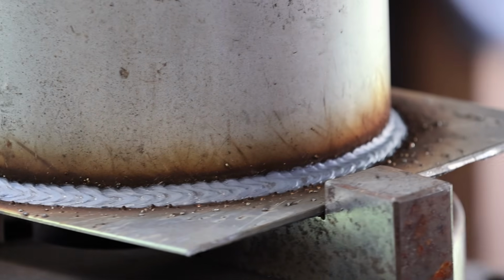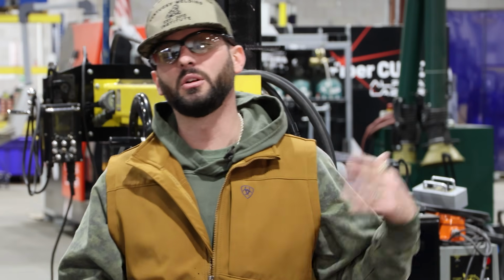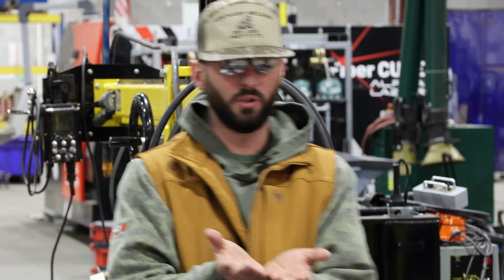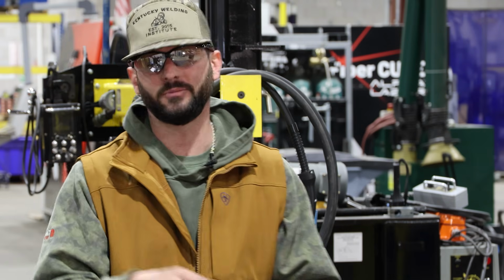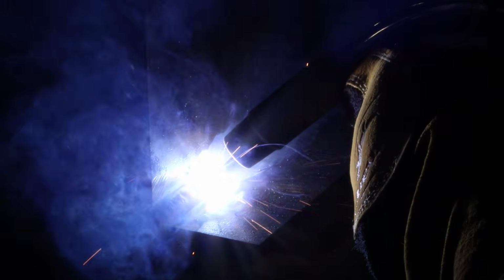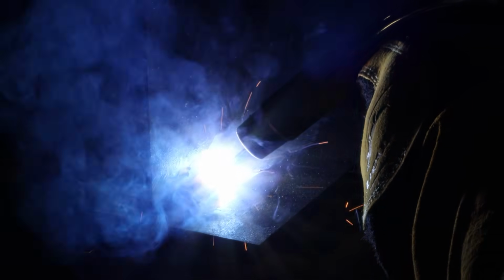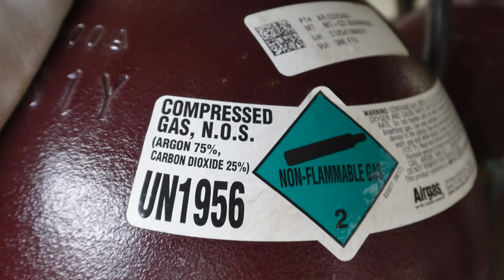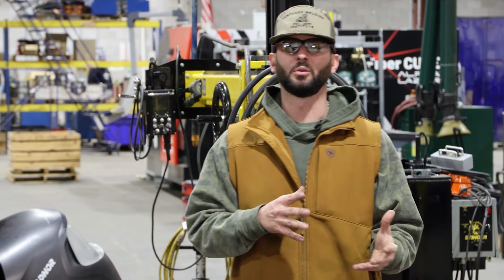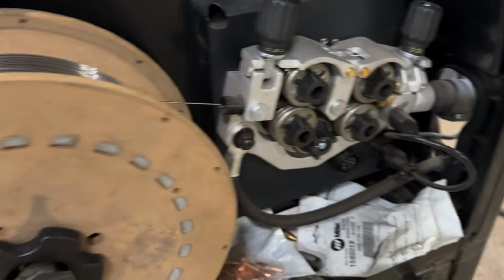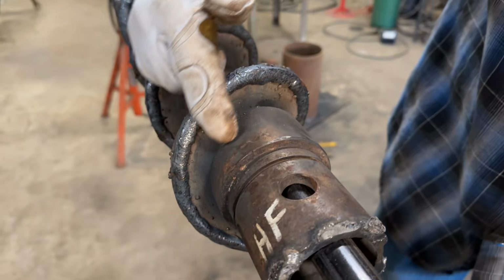Now, when it comes to flux core arc welding, especially dual shield, which requires an external shielding gas along with the flux on the inside of the wire, this is a really common process to use one of those argon CO2 mixes. Somewhere around that 75-25 is usually pretty good for it. Same thing goes for metal core arc welding. They have their own special blend of argon and CO2 that makes it weld just right.